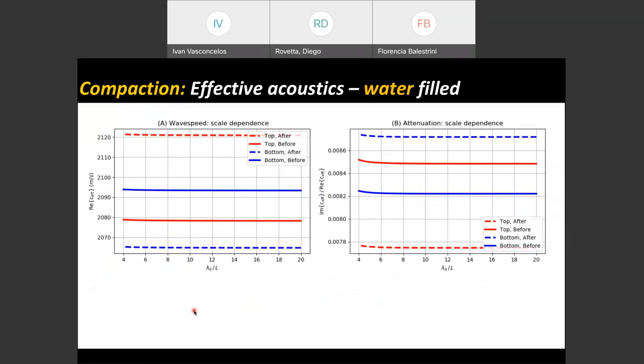Now, you can see here that we go from 4 times that length scale to 20 times that length scale. This means that on the left of these plots, we actually have a high frequency, and on the right, we have a low frequency. In real terms, for this size of an experiment, this here is 1.5 megahertz, and this here is about 0.5 megahertz, just so you know.